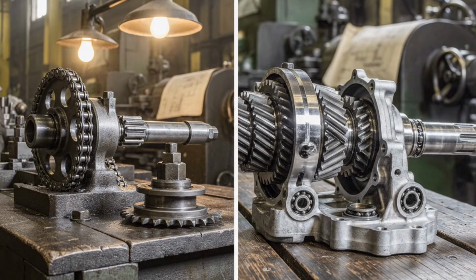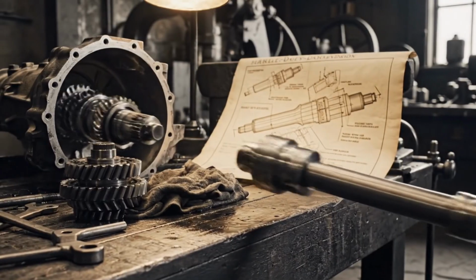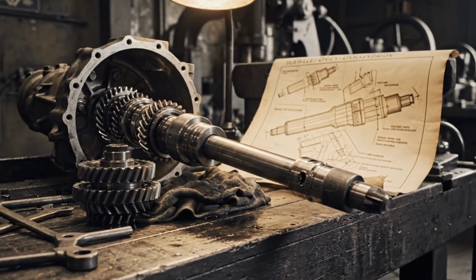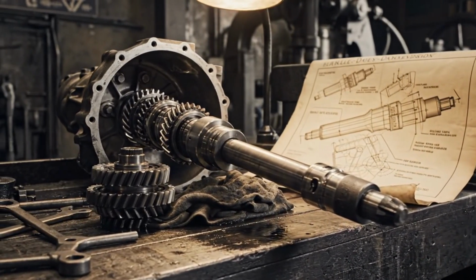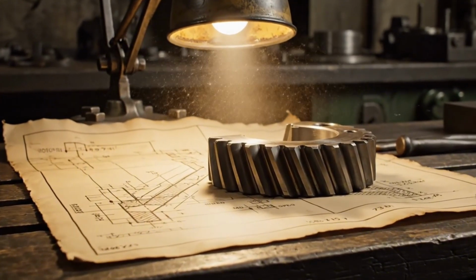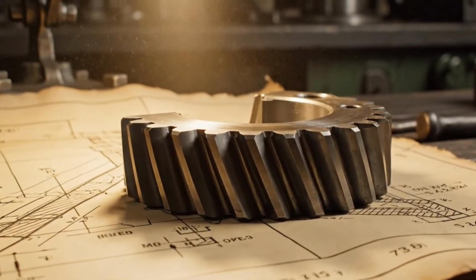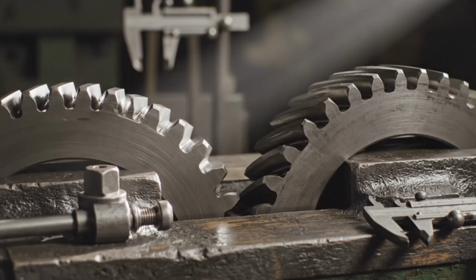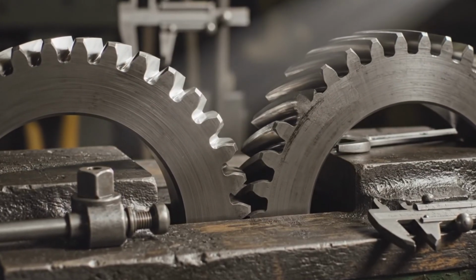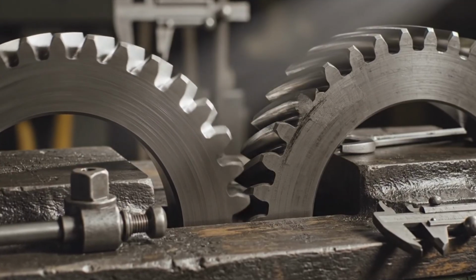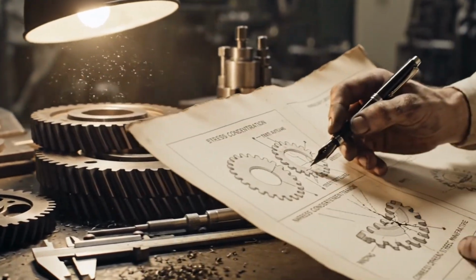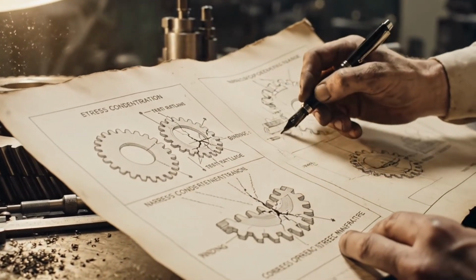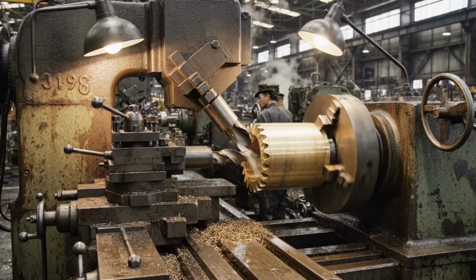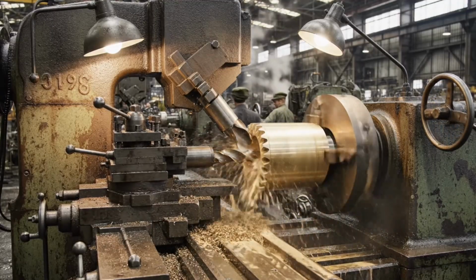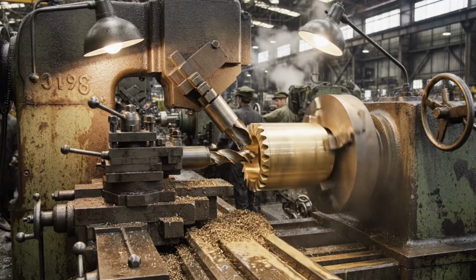The shaft drive was one of the most significant technical departures from conventional Harley practice, and one of the most demanding systems to manufacture correctly. Instead of a chain running from a front sprocket on the engine to a rear sprocket on the wheel hub, the XA used a sealed assembly of bevel gears and a steel drive shaft. A bevel gear at the transmission output redirected the engine's longitudinal power into a lateral shaft that drove the rear wheel axle. The gears had to mesh with almost no play between the teeth. Too much clearance, and the gears would rattle, wear unevenly, and eventually fail. Too little, and they would bind under load, generating heat and stress that could crack a tooth.